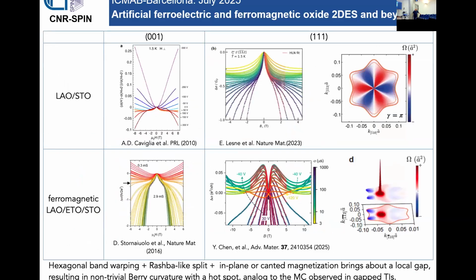Just to summarize, this is the situation for oxides in general. This oxide two-dimensional electron gas. This kind of graph is, if you perform measurements on LaTiO3/SrTiO3 (001), LaAlO3/SrTiO3 (001), and also in LaAlO3/SrTiO3 (111), essentially you get magnetoconductance corrections which are trivial. The one you can explain with the weak localization and anti-localization theory. And only in our case you get this anomaly that is due to the non-trivial Berry phase related to the presence of hot spots of Berry curvature along the Fermi surface.